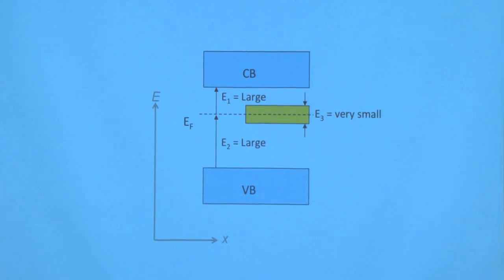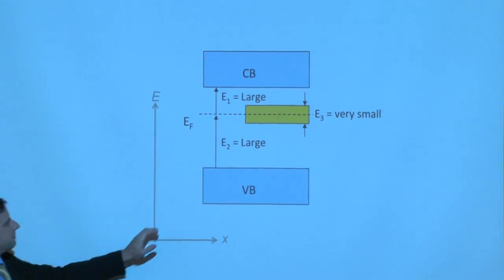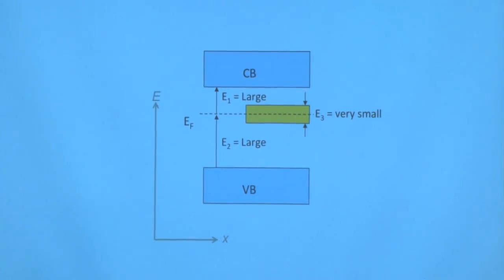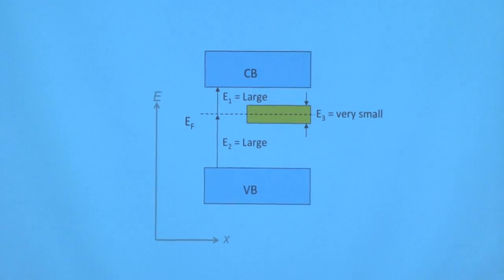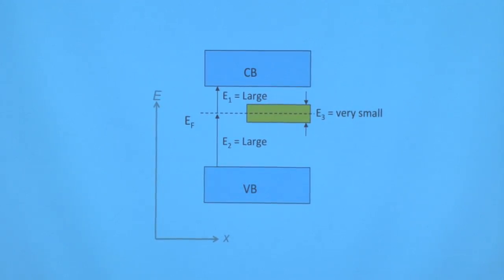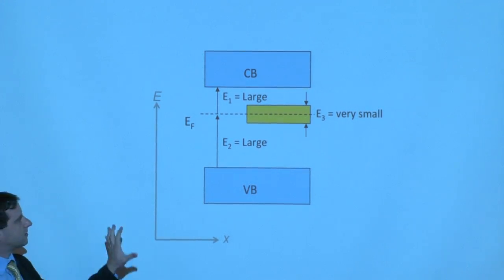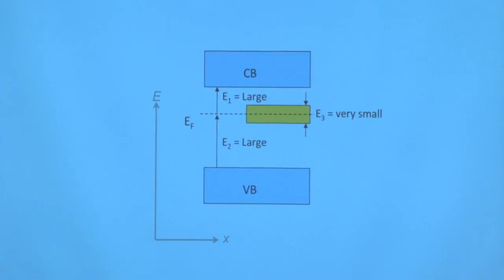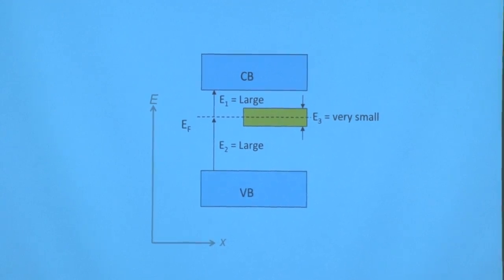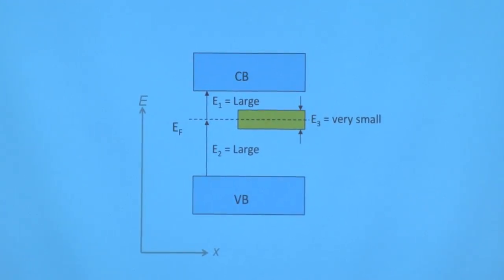On the other hand, if we come in with a high energy photon, or a moderate energy photon, let's say in the visible, it doesn't have quite enough energy to excite from that orange band into the conduction band, nor from the valence band into the orange band, the intermediate band there. And that's the general principle of how transparent conducting oxides function. You can have indium-doped tin oxide, for instance, ITO, as a classic example. And this is the basic premise.